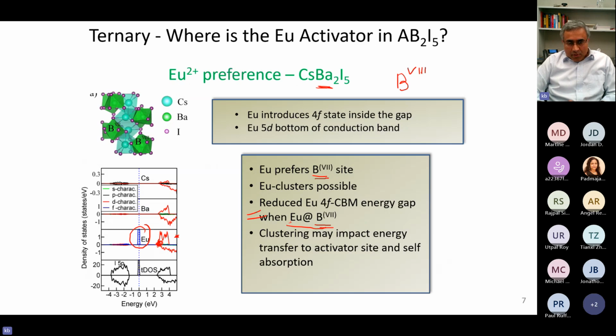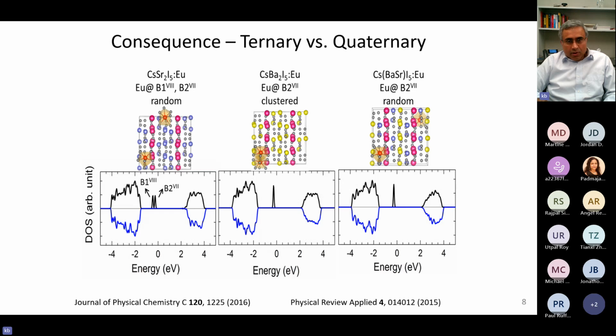But coming back to this problem of europium preferring the B7 site or the 7 coordinated site, and europium preferring to form clusters or europium rich regions and europium poor regions within the crystal, which will be a problem. In order to circumvent that problem, what we said is, why not try something like this, a quaternary alloy where you have cesium, barium, strontium iodide. You grow the crystal as a mixed crystal like that with barium and strontium instead of pure cesium strontium iodide. People have grown that, or instead of pure barium iodide, people have grown that too. We said, why not do that in order to circumvent the problem of clustering and europium preferring the B7 site.